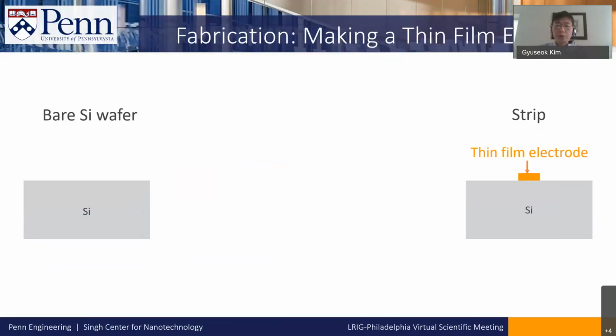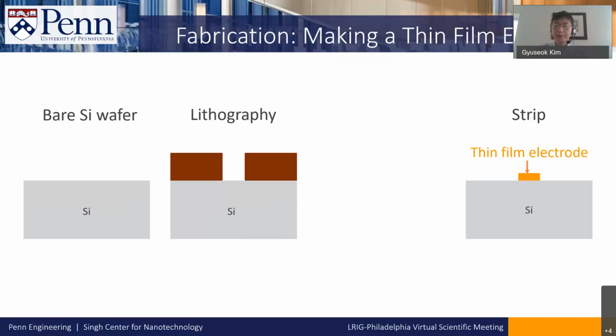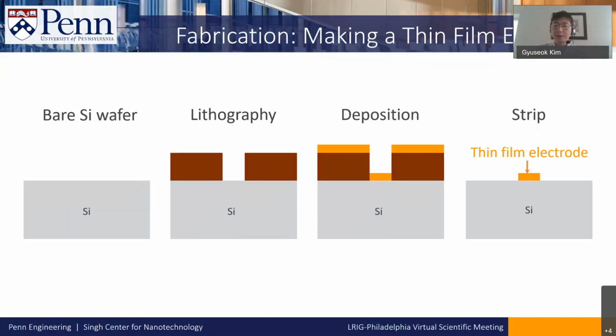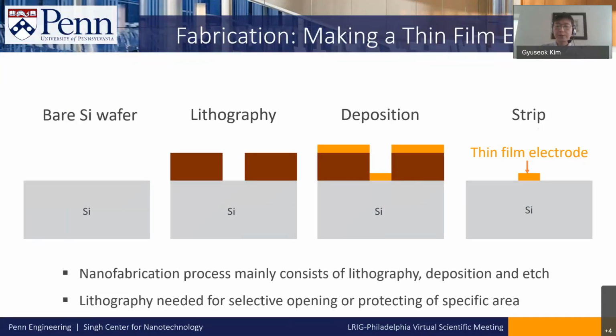Let's think about one more example. Here's a bare silicon wafer on the left side. On the right side, we want to deposit a thin film electrode. How can we make this? We have to do lithography first, and then deposit the electrode material. Then if we remove the photoresist, we end up with a thin film electrode sitting on the silicon. From those three examples, we can conclude that the nanofabrication process mainly consists of lithography, deposition, and etch processes. And one more thing: lithography is needed for selective opening or protecting of some areas.